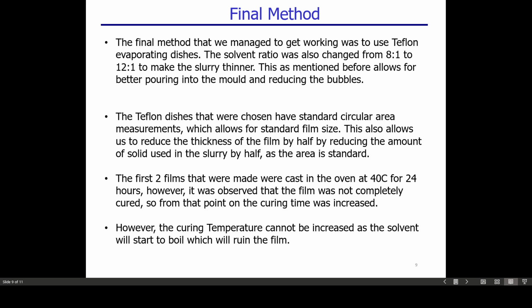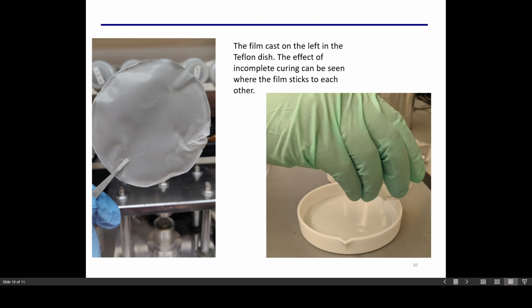However, we can't simply increase the curing temperature, as the solvent would start to boil, as it is an alcohol-based solvent. And on the left, you can see one of the successful films that we cast, and on the right is the process of pouring the solvent carefully from a lower height to stop any introduction of bubbles into the film.